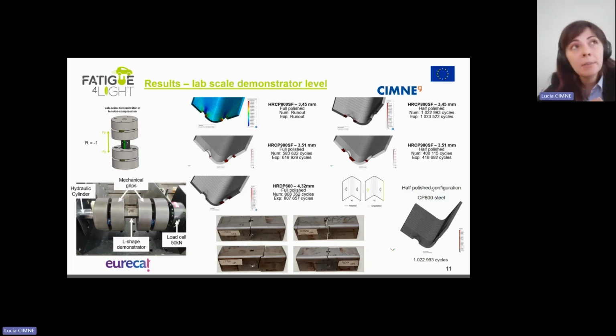And the experimental campaign, which was done at lab scale demonstrator level, included several stress amplitudes with a reversion factor of -1, so fully reverse cyclic loading. And here you can see a comparison in between the life which was obtained through the simulation, the numerical analysis of this geometry, as compared to what was seen experimentally in the campaign done by our colleagues at Eurecat. You can also see the failure mode, which is observed below. And this is interesting because with the numerical approach that we've developed during the Fatigue4Light project, we've seen a really good agreement in between the life obtained at experimental level and in the numerical simulation.